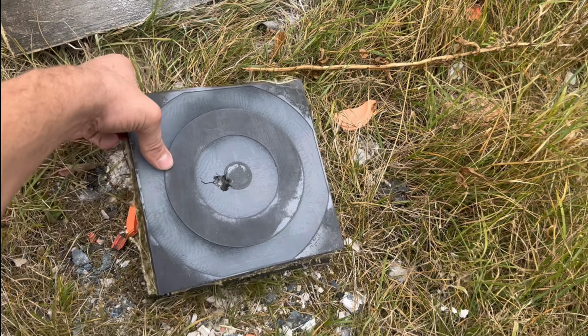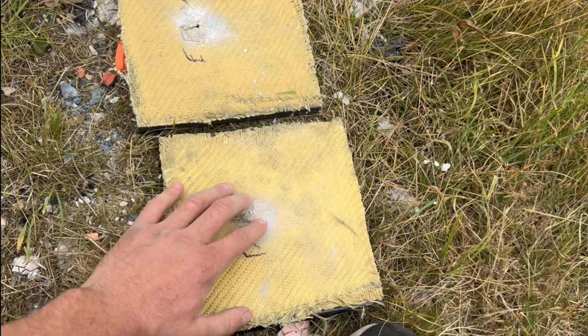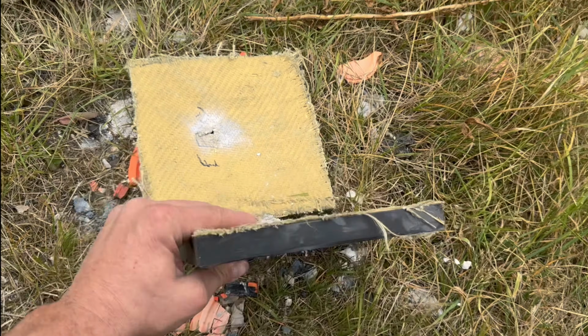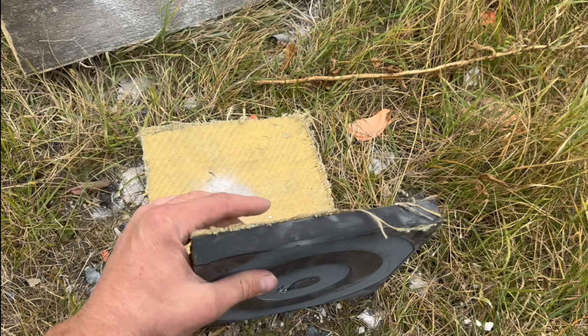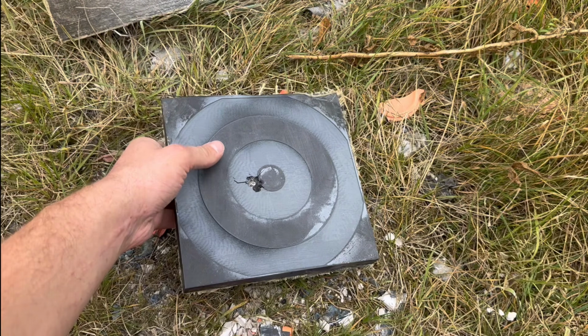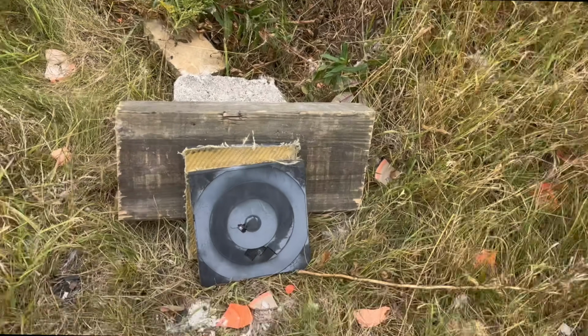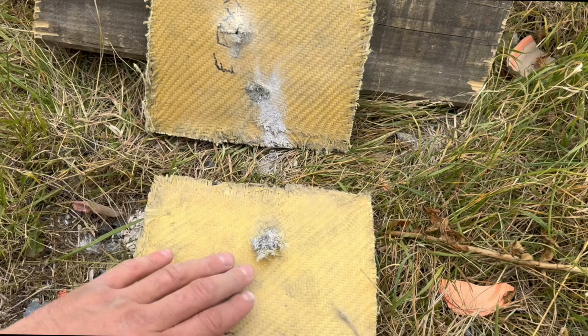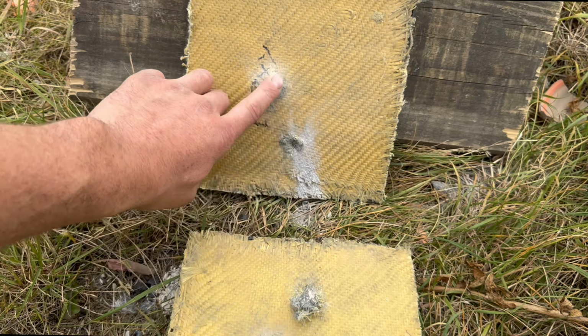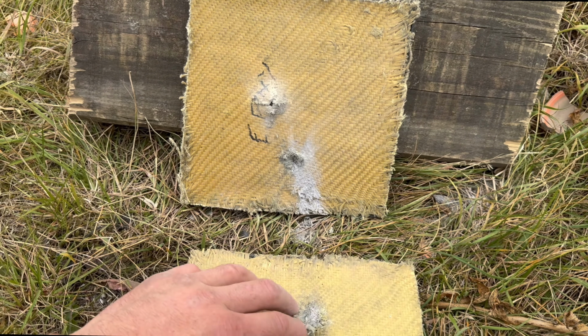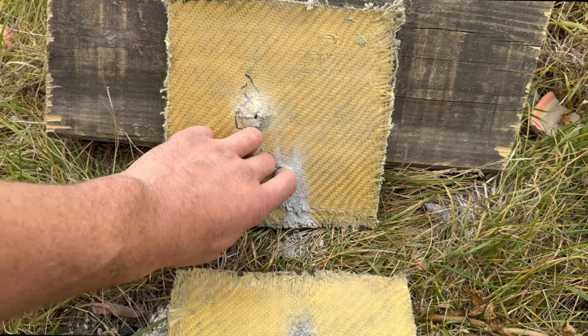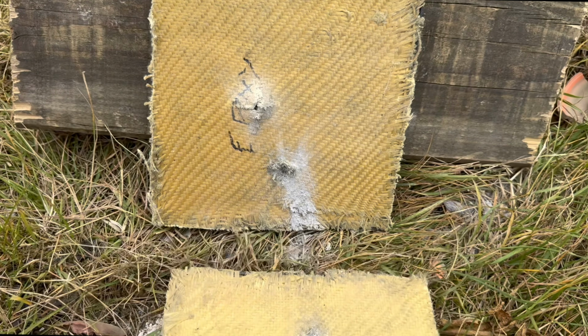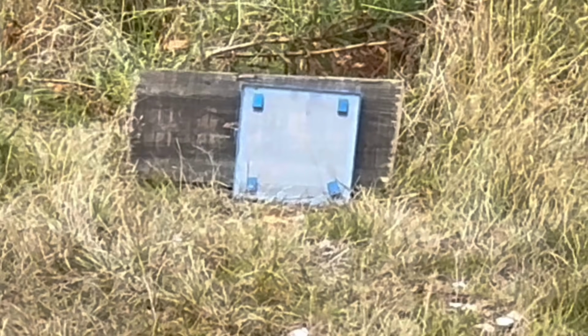I've now got the 2 Kevlar pieces with the polyurethane at the front, and I'm going to put it behind the epoxy to see how far in the bullet actually goes. And that did stop on the second plate. It went deep into the Kevlar, appeared to stop about at the ceramic layer. So again, you can imagine if you had 10 millimeters of Kevlar, that probably would have stopped it. But moving on to the most interesting piece, the glass and the polycarbonate.